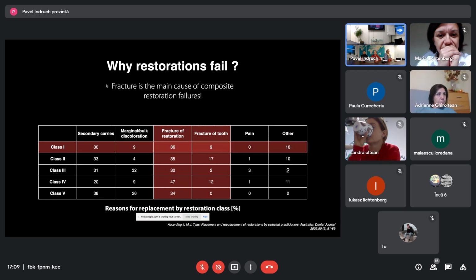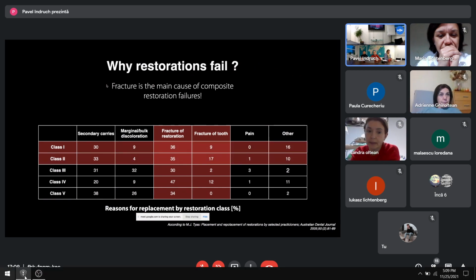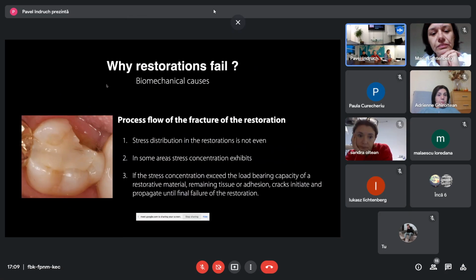You can see that for class 1 and class 2 cavities, fracture of restoration or fracture of tooth is the most common reason for failure. This is a picture of a very common failure associated with the uneven stress distribution in the restoration and the origination of a stress concentration in some critical areas of the